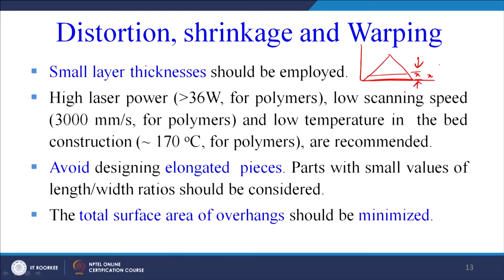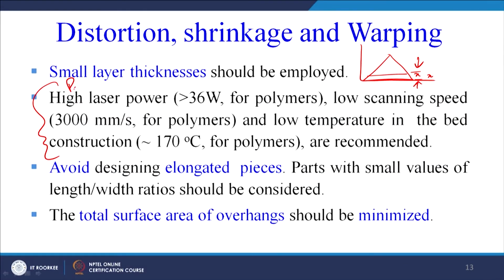High laser power, maybe greater than 36 watt for polymers, low scanning speed, 3000 millimeter per second for polymers, and low temperature in the bed construction, approximately equal to 170 degree centigrade for polymers, are recommended. Very good guideline for polymers, specifically for making prototypes out of plastics. The laser power is given, the scanning speed is given, and the bed temperature is also given. If we keep all these parameters in mind while doing the rapid prototyping process, we will be able to make good prototypes which will not be prone to failure.